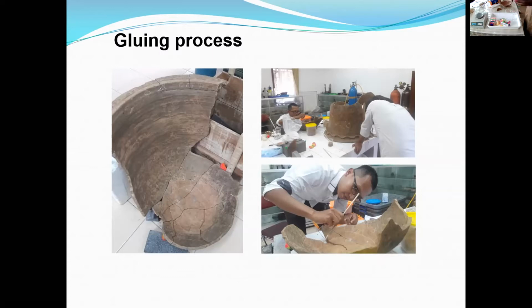And this will take relatively longer time compared to when we use synthetic adhesive. Because the adhesive itself might take about 20 minutes to dry off. To achieve the strongest adhesive effect that we want, it will take 4 to 5 hours. But after the initial 20 minutes, we can begin attaching a different fragment.